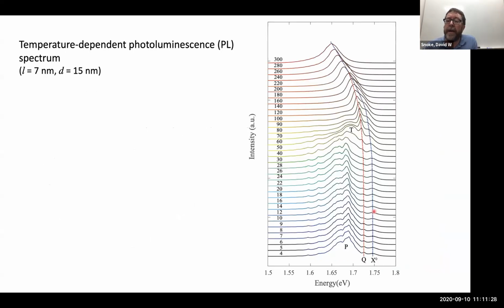Okay, so here's some data. And this is in a variable temperature cryostat. Starting at low temperature, we just pump non-resonantly and then increase the temperature while keeping the laser power the same. And several different features here. The nice thing in general, I would say, is these monolayers and tungsten diselenide in particular are well studied. So every line is pretty much known in the literature. You can go and just look up exactly what you got. And of course, the other thing you do, which we did, is you can make monolayers of this material. And anything that exists in just a monolayer, you're going to see just by itself.